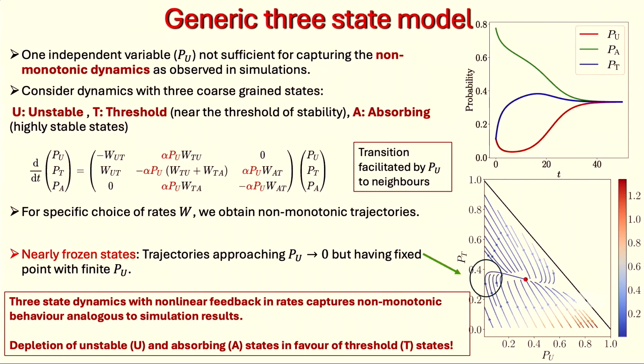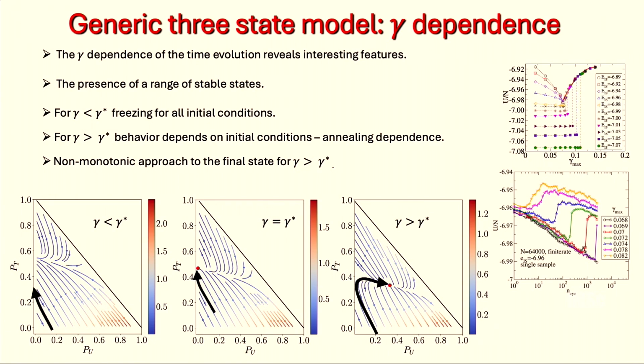I can represent this in a flow diagram where I have the population of unstable states and the threshold states. What you see is this initial behavior where Pu, the unstable state population, continues to decrease, and for some initial conditions indeed I just go to 0. But if I have a large enough Pu, after an initial phase where it decreases, it turns around and goes to a fixed point where the unstable state population is finite. This is the behavior that I find when I have yielding in the system for large enough strain amplitudes, and I can look at how the flow of states changes with respect to the strain amplitude, and this non-monotonic dependence